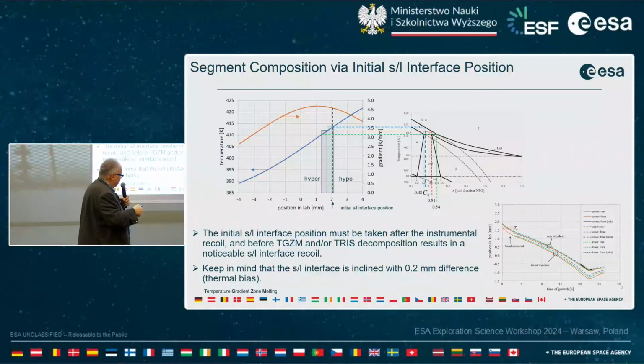Then, yeah, let me concentrate a little bit on the difficulties of this problem. One of these problems is this peritectic phase. It's very flat, and you can see here the temperature inside the transparent alloy device. And the peritectic phase covers only this small region. So small mistakes in balance or local differences make a huge difference for us.